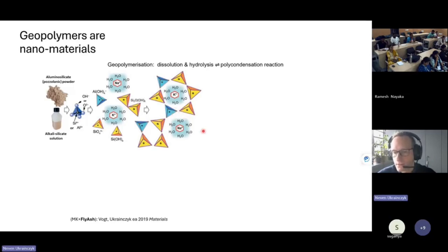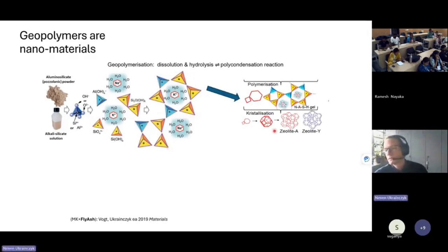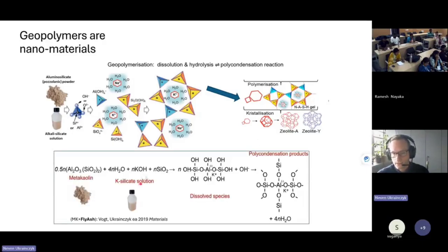You are releasing water, so it's the opposite of cement hydration, where you bind water. Here actually you are releasing water in a polycondensation reaction, and you are making this three-dimensional polymer. That's why it's called geopolymer, but it's made from silicate, not from carbon organic, but inorganic, an aluminosilicate polymer network. If you would polymerize this further and crystallize, you would get zeolites. So they are basically amorphous analogs of zeolites. And you can see this reaction written also chemically. You can see these oxo bridges here.